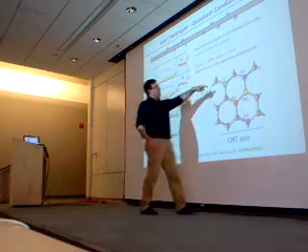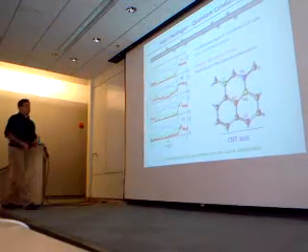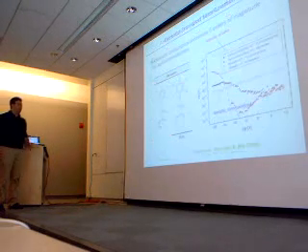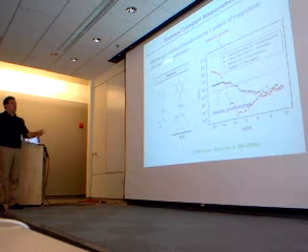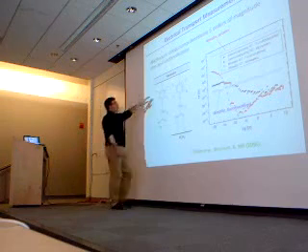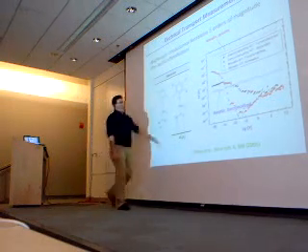Even 30 molecules here are able to completely destroy the conductance. Basically because when you attach a molecule, you transform the carbon atom from sp2, bonded with 3 covalent bonds, to sp3 with 4 covalent bonds, and that's a very strong scattering center. And I showed these results at IBM, and the next year they actually did the experiment on the same system, in which they took a nanotube and functionalized it with the same sort of ligand.